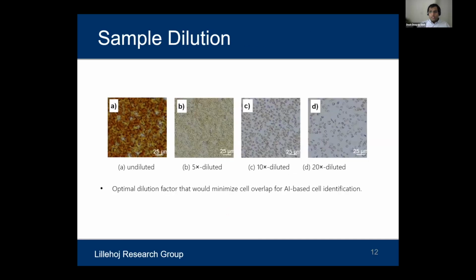So now the second challenge was that because it's an optical based technique and the gap size is only 30 microns, we didn't want the cells to overlap. The majority of the cells in blood are RBCs, and you could see in the first image the undiluted blood where RBCs are all over the place. We cannot identify them, because the CD4 cells tagged with beads would be on the other side of the RBCs or totally opaque or hidden behind them. So we tried doing dilution, and we figured out the optimal dilution was 10x dilution, because it's an optimization problem: if you keep on diluting the sample, the volume that you need to process to get a statistically significant answer would also increase.